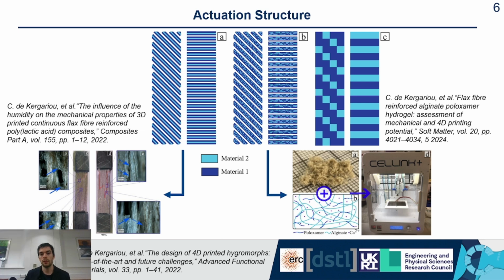It's not so much the orientation which is important, it's the distribution of material. So you have two different materials that behave differently with humidity. One wants to expand more than the other. So if you distribute this material differently between the layers, they have different will of expansion again. And so if you contact these two different layers, you have stresses at the interface and so bending and actuation once again.